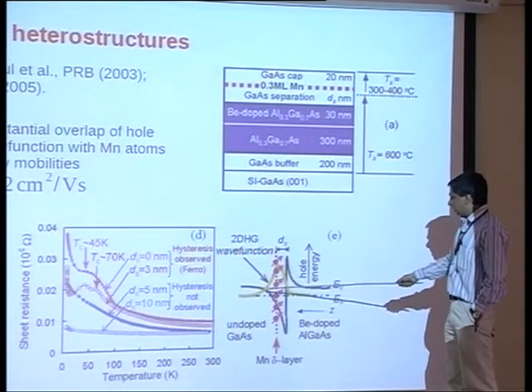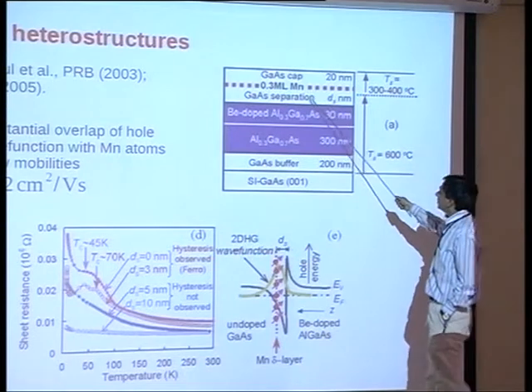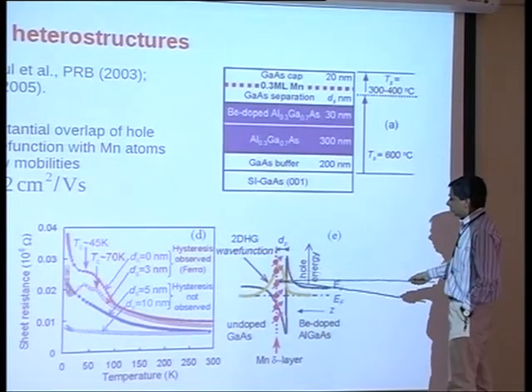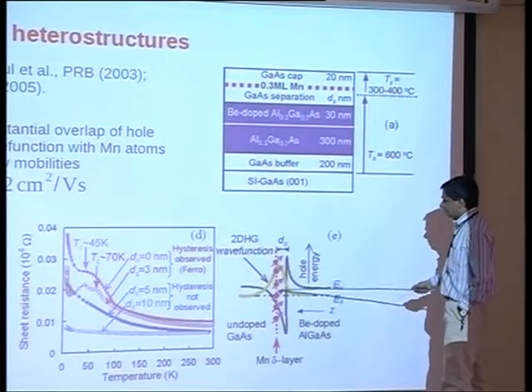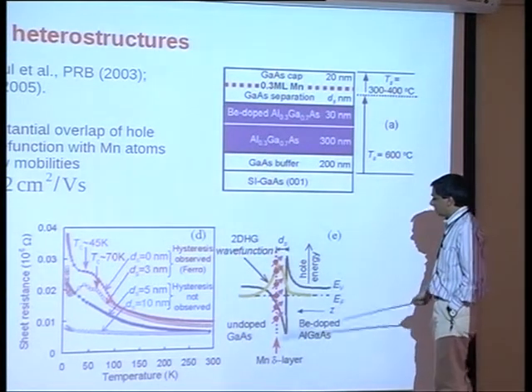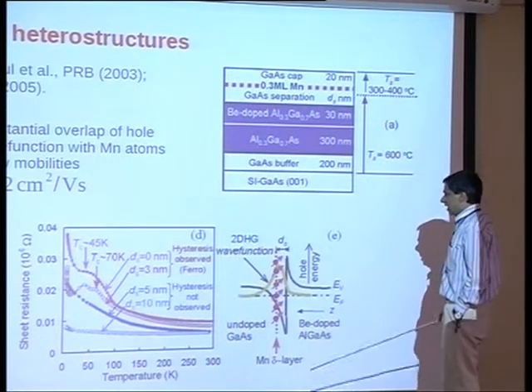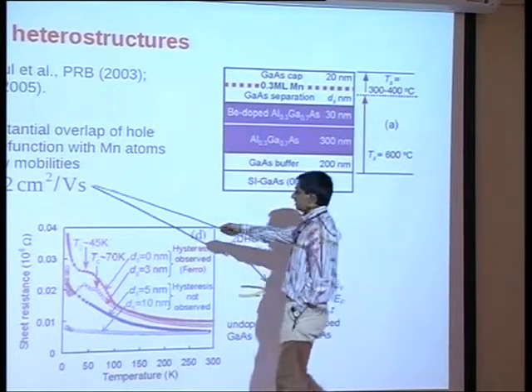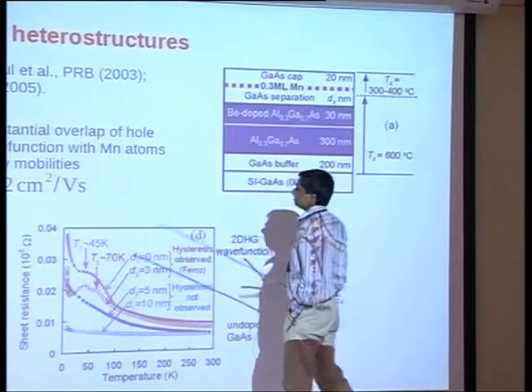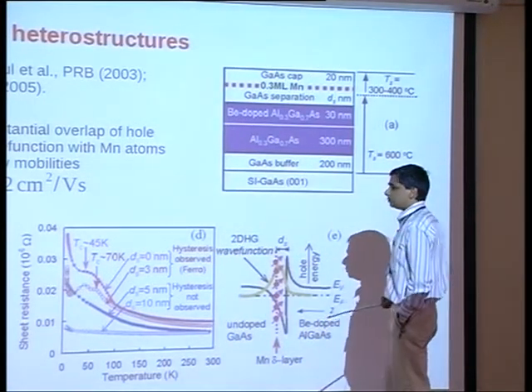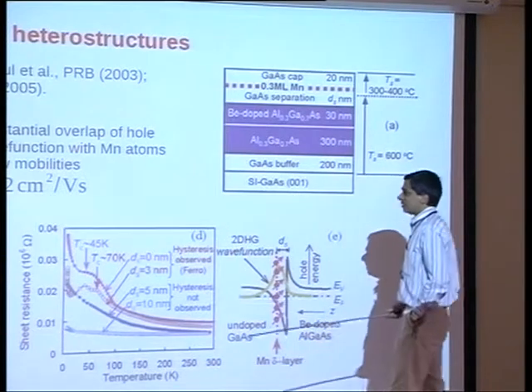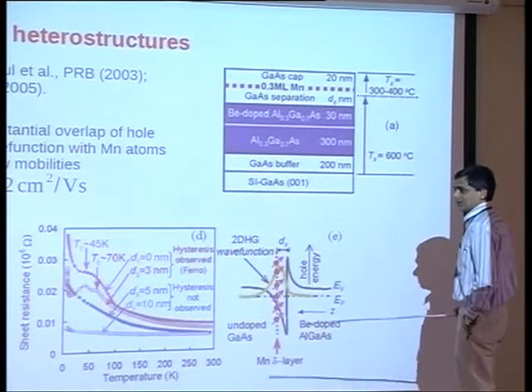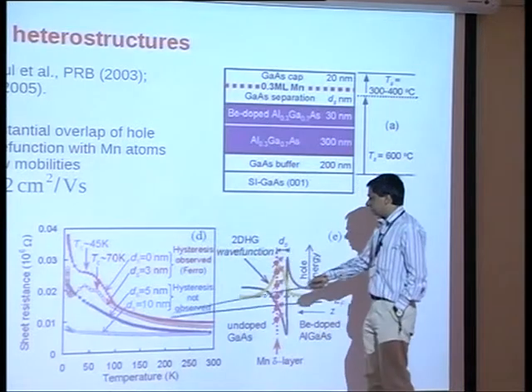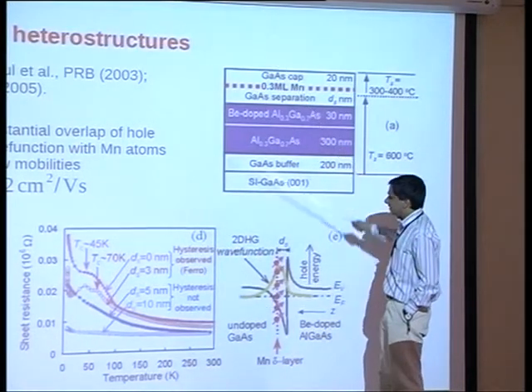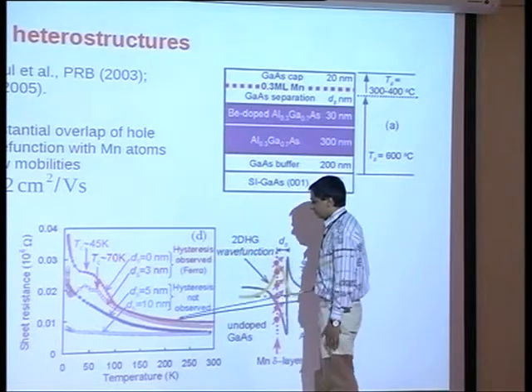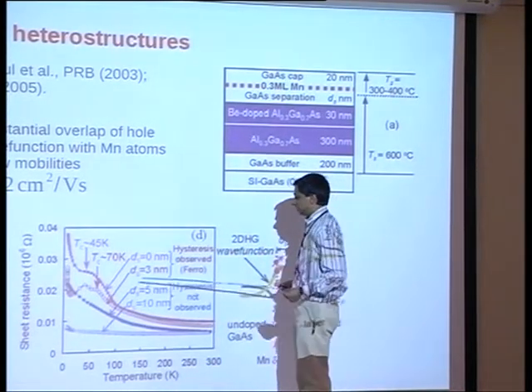So this is kind of a self-defeating heterostructure, because the wave function overlaps quite strongly with the manganese dopants, and it will have very low mobilities. For example, these samples have a typical mobility of 2 centimeters squared per volt second, as opposed to 10 to the power of 5 for the gallium arsenide devices I showed you. So it's that bad. Nevertheless, you do have a controllable system where you can control magnetism through gate voltages.